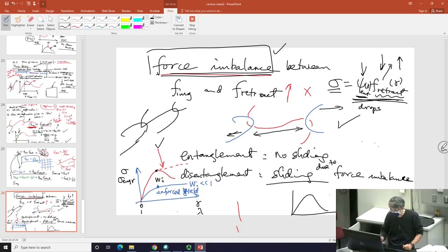And the remaining ones, if they have not reached force imbalance, may still stretch. But the overall trend is that you start to lose some contribution, and that's how force comes down. So that's not a very difficult point in that sense, meaning not very difficult that this doesn't follow the dashed line, because you start to lose them.